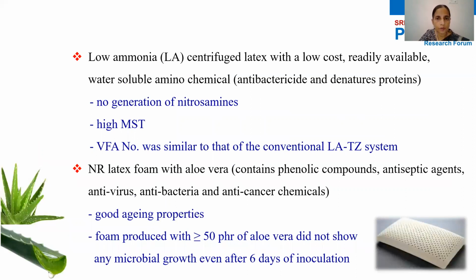Low ammonia centrifuge latex is conventionally prepared with the secondary preservative system TMTD and zinc oxide. However, TMTD generates nitrosamines, and there is a search for alternatives for the TMTD.